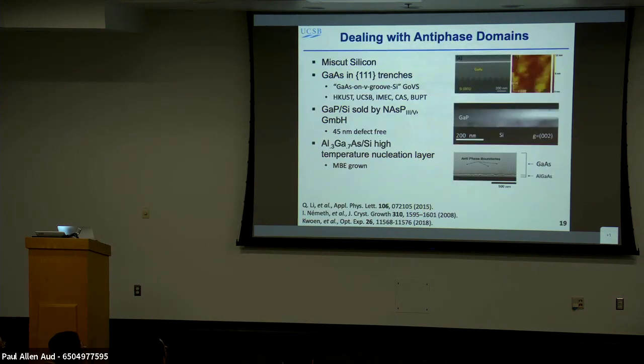How did we get there? Because they weren't good lasers 2 years ago. Well, you have to deal with the antiphase domains. You have to deal with dislocations. And so you can deal with the antiphase domains in a few different approaches. So one is to work with miscut silicon, several degrees off. So everything until 2 years ago was based on off-cut silicon. Today, all the groups around the world are doing on-axis silicon. So it's fully integrable with conventional silicon.